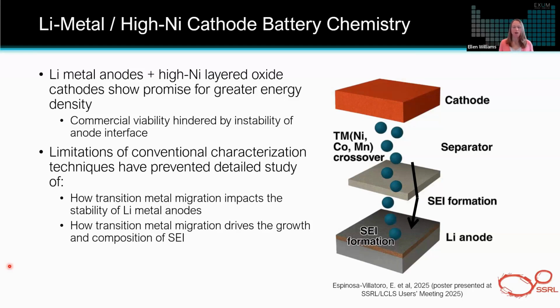So you can see this diagram on the right here, which was presented by our colleague, Eric Espinosa Villatoro, at an SSRL users meeting last year. And many of you may be familiar with this particular battery chemistry. The combination of lithium metal anode with a high nickel layered oxide cathode has a lot of promise. It can have much greater energy density than some of the traditional lithium ion chemistries, but we also know that it's not quite commercial yet.